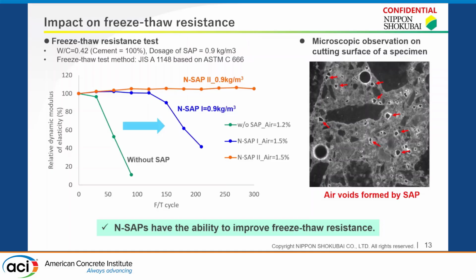On this slide, we focus on the impact of SAP on freeze-thaw resistance. We have confirmed that our new SAPs can significantly improve freeze-thaw resistance compared to the control mix without SAP. And these air voids created by SAP act similarly to entrained air.